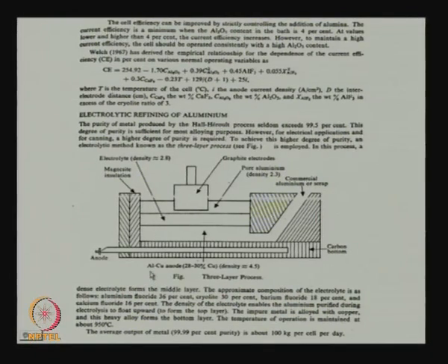We make an alloy of impure aluminium and copper. This is 28% to 30% copper. That makes the density of the alloy about 4.5. Copper is very heavy. So, this alloy of aluminium, which is actually the impure aluminium we are calling it, stays at the bottom. We find an electrolyte which is lighter than this, and it is adjusted to 2.8. On top of that, pure aluminum, which is 2.3 density, will float.